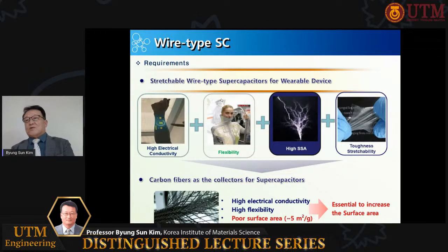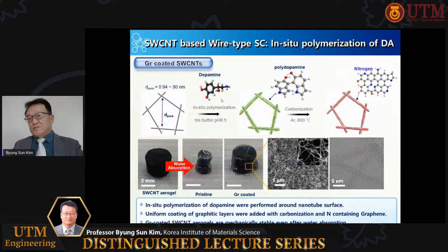Carbon fibers may be used as the collector for supercapacitors since they have high electrical conductivity and high flexibility. However, carbon fibers have a poor surface area, which is only 5 square meters per gram. And this needs to be increased since the performance of the supercapacitor is dependent on the specific surface area. In order to increase specific surface area, our strategy was to decorate the single-wall CNT aerogels, which have the largest surface area and good electrical conductivity, around the carbon fiber surface.